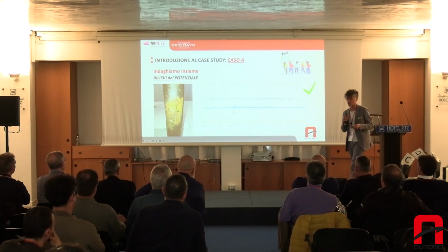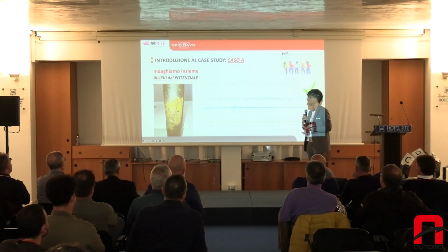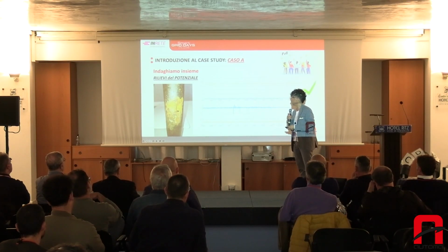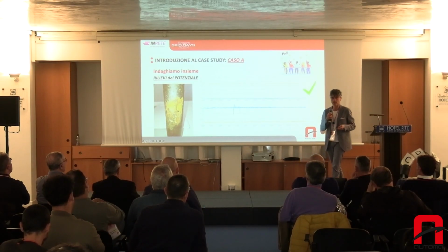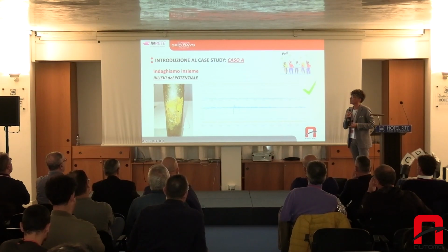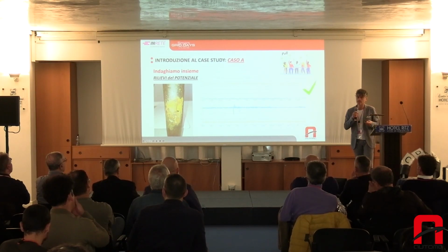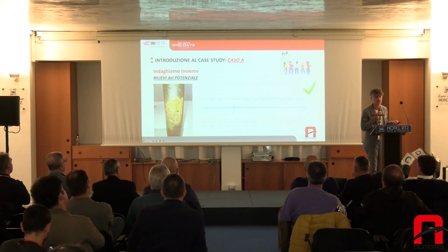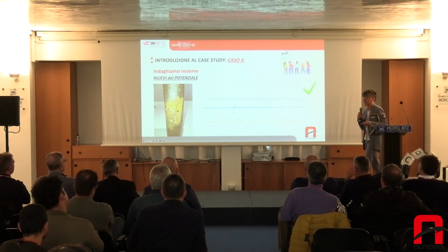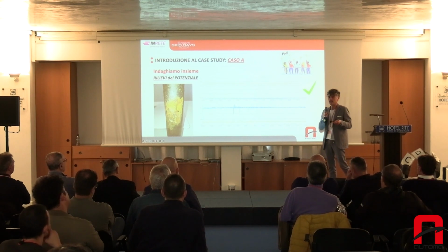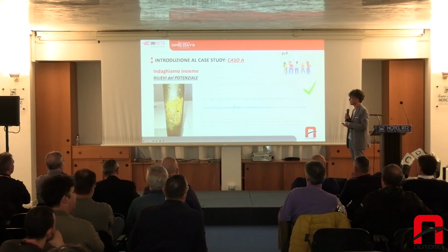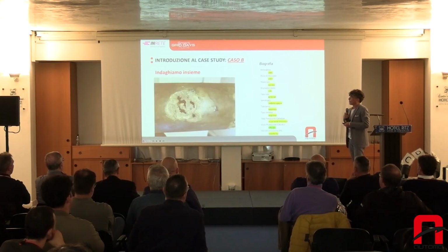This type of protection, the graph is telling us, means that the situation has always been like that. The protection was there since 1985, and the coating was damaged to such an extent that current was not capable of providing the effective protection.